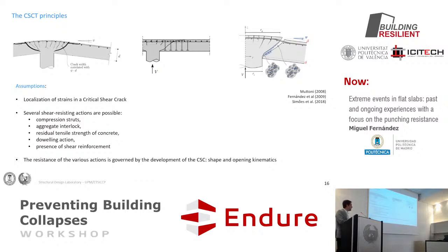And so what is the theory saying? That the strains are localizing in a critical shear crack. This is what we were seeing before, despite the fact that we might have shear reinforcement. And then it's simply saying that this critical shear crack, through its shape and kinematics, the curvature it has, and the location it has, determines what capacity we can transfer through compression struts that we have below, aggregate interlock, so friction between the lips of the cracks.